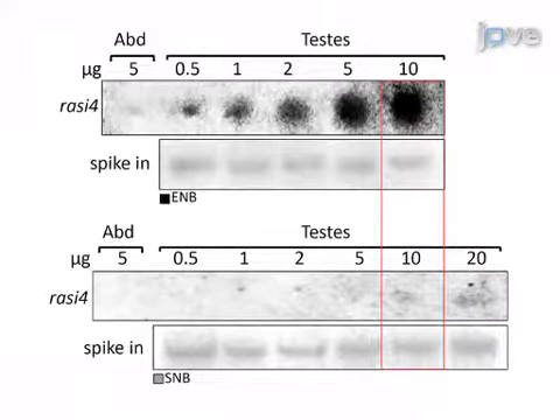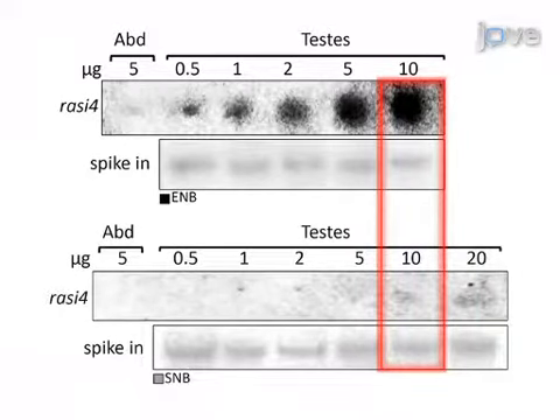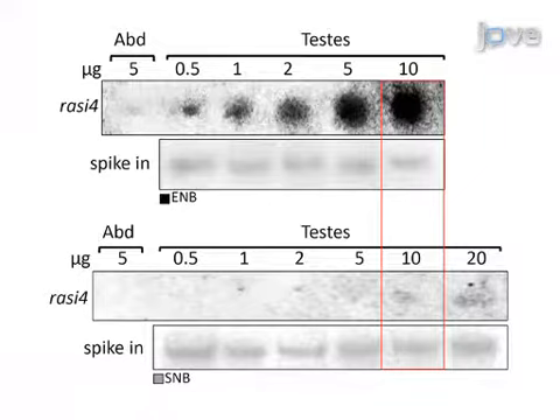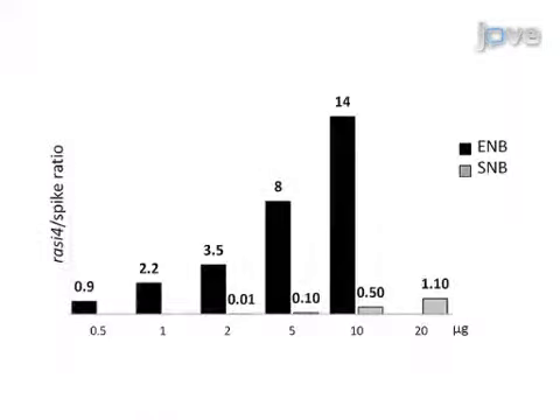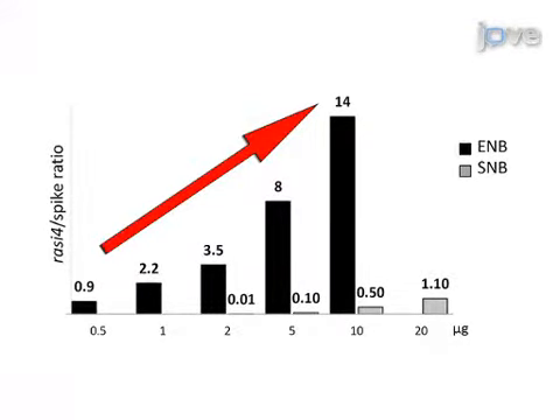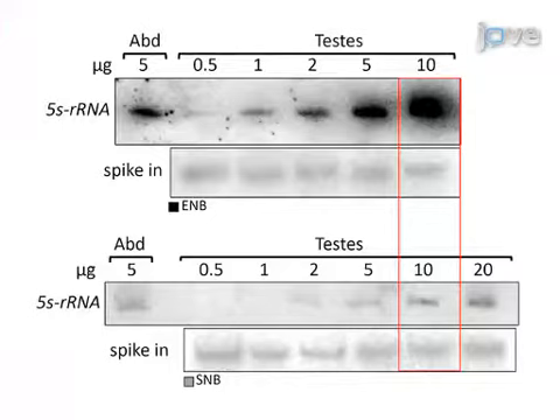The Enhanced Northern Blot, or ENB, ensures higher sensitivity with respect to the Standard Northern Blot, or SNB, as illustrated by this figure of the autoradiographic detection of the piRNA RASI4 along a titration of total RNA extracted from adult fly testes. The signal proportionally increases with the amount of fractionated RNA, indicating that the dose-response ratio lies in a linear range of detection. The method successfully applies to long RNAs as well as 5S ribosomal RNA, provided that they get a free 5' end and a length suitable for acrylamide fractionation.